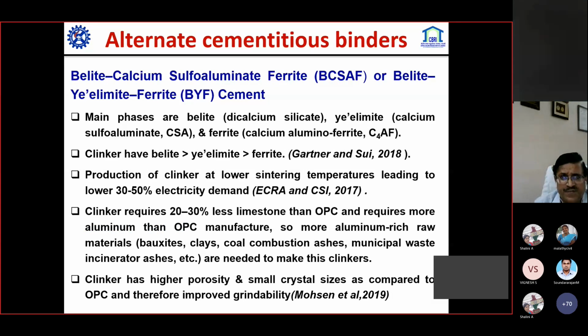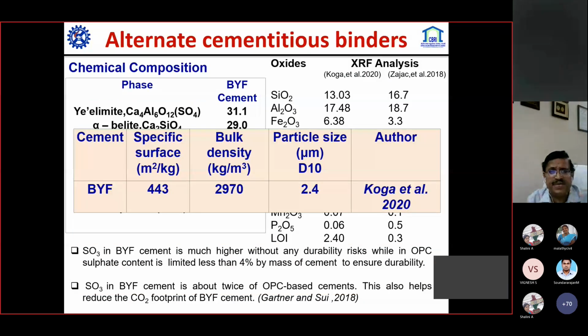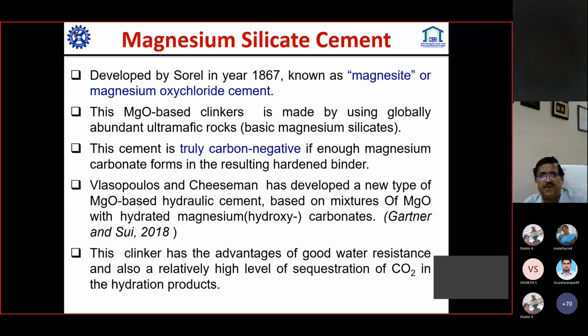Belite calcium sulfoaluminate ferrite. It is another type of cement. Here, clinker requirement gets reduced by up to 30% as required in the OPC, and by this we can reduce both energy as well as the CO2 emissions, because this will be lesser. So I am quickly showing the properties of this cement: specific surface is about 443 meters square per kg, density is 2.97, our specific gravity is 2.97, particle size D10 is 2.4, and different researchers have worked on this, and they have found this one I was telling.